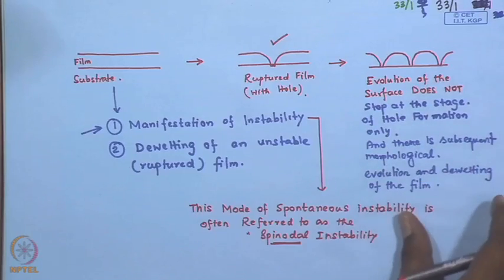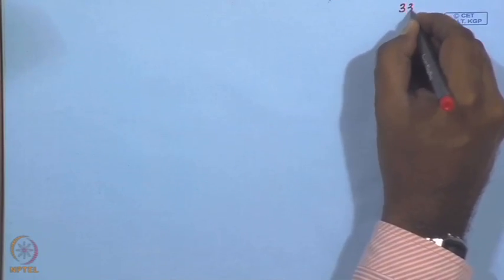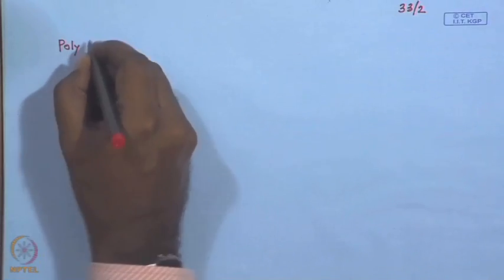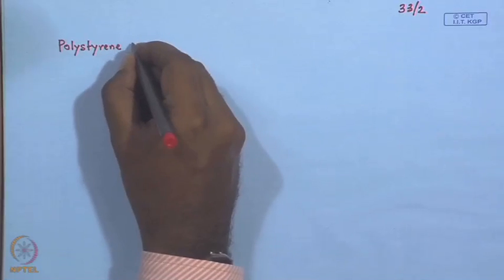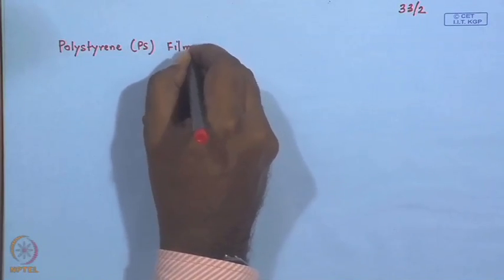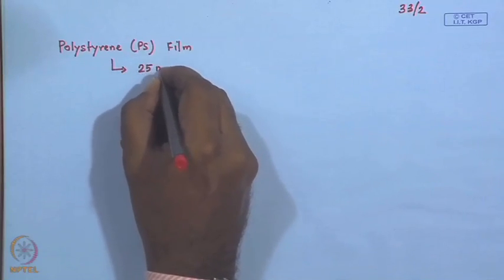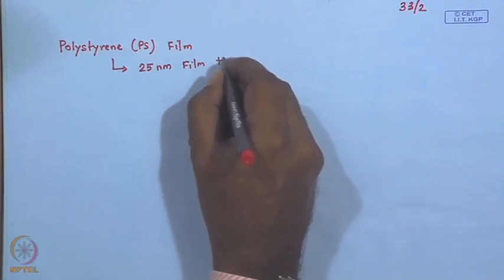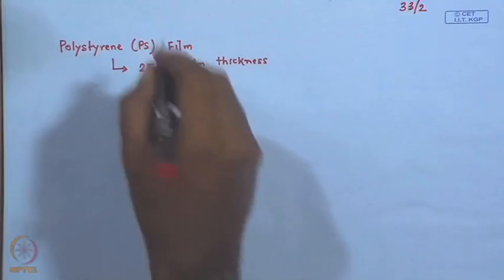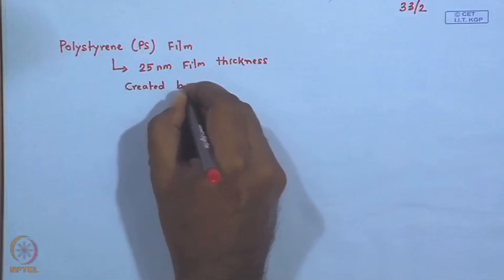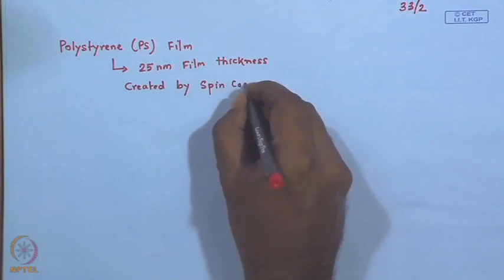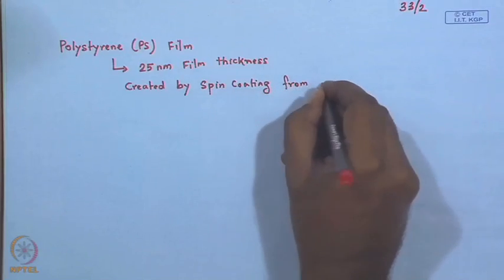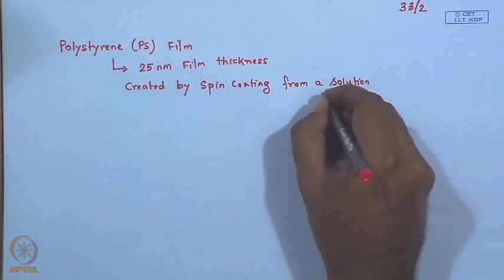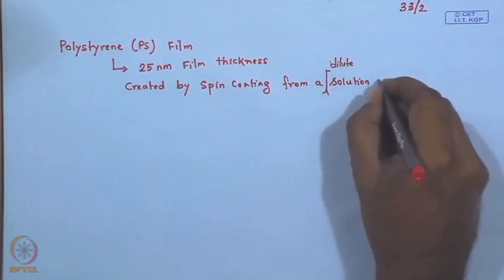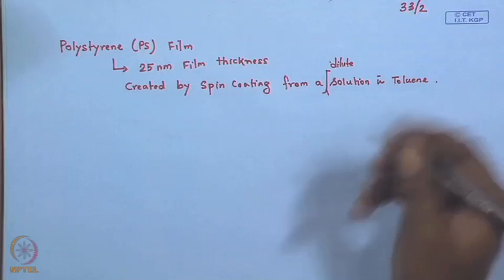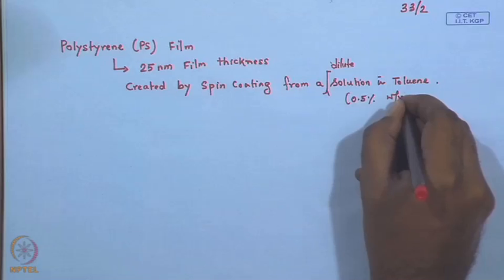So, we have taken a polystyrene film. It is a very common model system. We will talk in greater detail about dewetting experiments. The film thickness was of the order of 25 nanometer, which was created by spin coating from a very dilute solution in toluene. Concentration lies around 0.5% weight by volume.